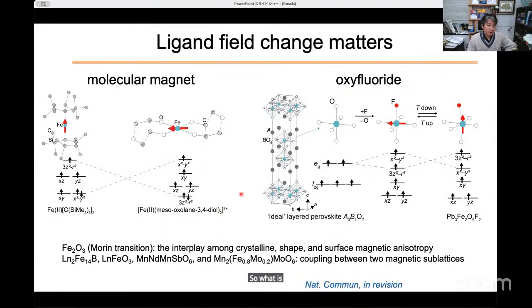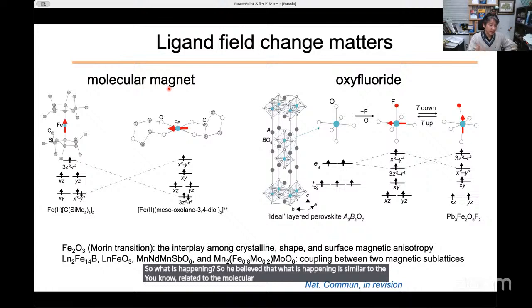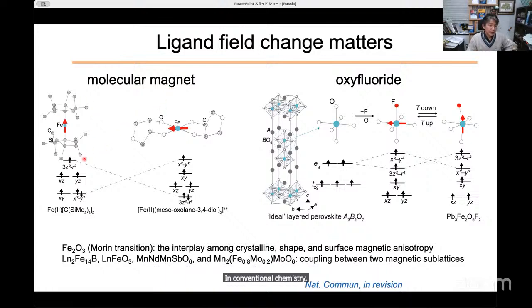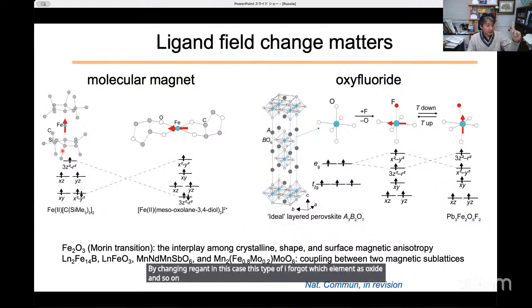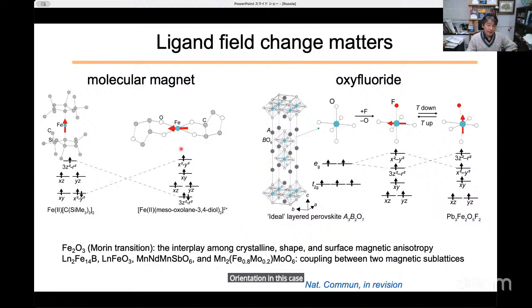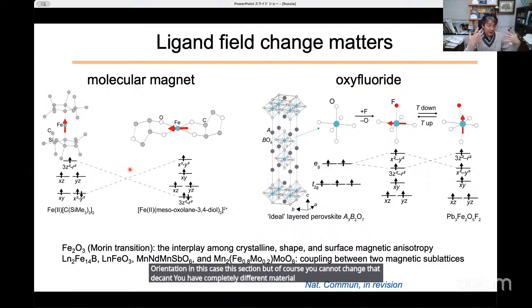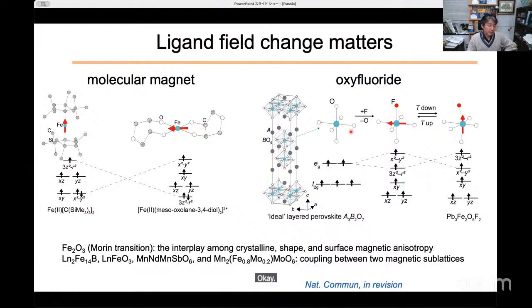So what is happening? We believe that what is happening is related to molecular or single molecular magnets. In coordination chemistry, this type of material shows spin orientation changes by changing ligand, in this case, I forgot which element, oxide and so on, you are able to control or change the direction of the spin moment. Okay, in this case, you have this up orientation. In this case, this direction. But of course, you cannot change the ligand here. That is a completely different material. But you can understand why in this case spins are up and in this case spins lie along the plane. Okay. But here, what is happening is as follows.